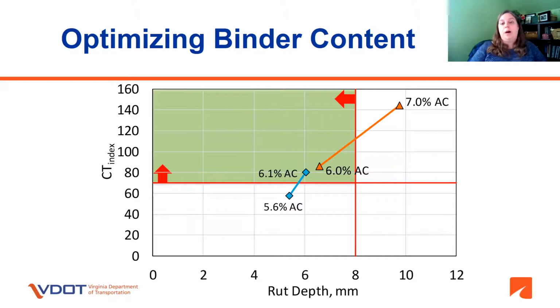To do this, we will optimize the asphalt binder content. The green shaded area shows what our target is in terms of test results. You can see in the blue mix that a 5.6% AC content, while passing the rut depth test, did not meet the CT index. That mix needed more asphalt in order to meet the criteria. At 6.1% asphalt, it worked quite well.